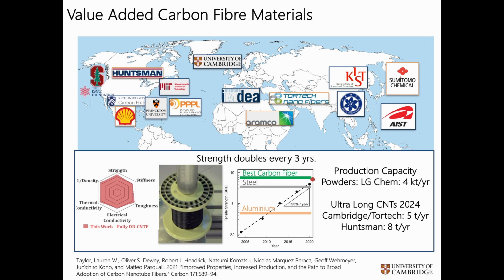And just in the last year, the best nanotube-based carbon fiber is on par with that. So the best is 7 gigapascals of strength. The best carbon nanotube is 6.5 gigapascals of strength. So really within striking distance with a lot of headroom, right? It's still growing at a given rate.